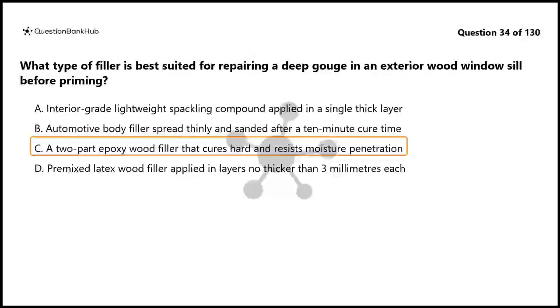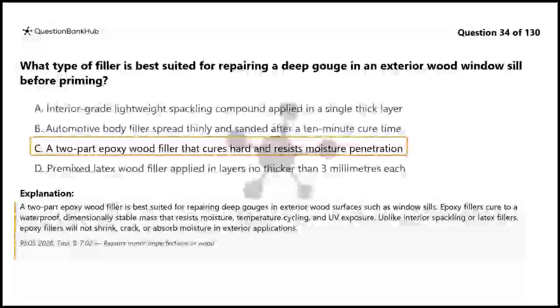The correct answer is C. A 2-part epoxy wood filler is best suited for repairing deep gouges in exterior wood surfaces such as window sills. Epoxy fillers cure to a waterproof, dimensionally stable mass that resists moisture, temperature cycling, and UV exposure. Unlike interior spackling or latex fillers, epoxy fillers will not shrink, crack, or absorb moisture in exterior applications.